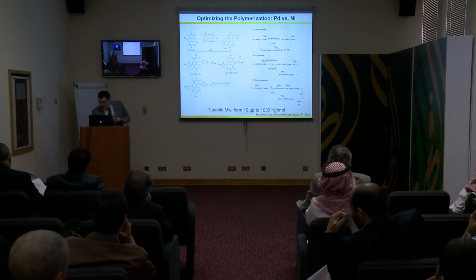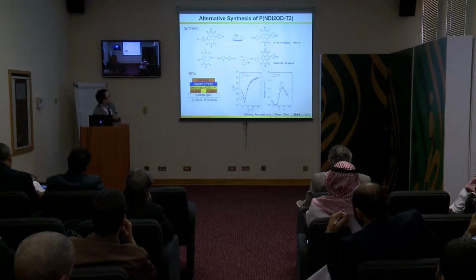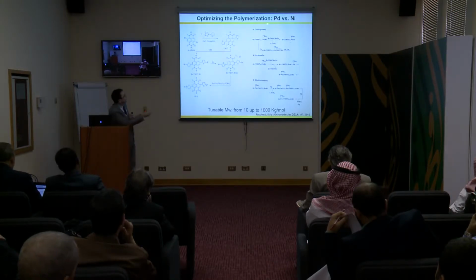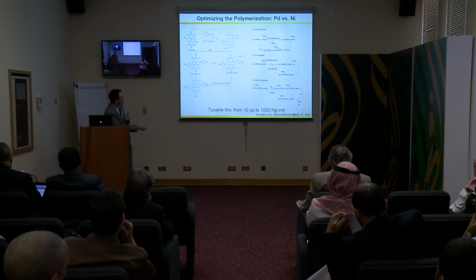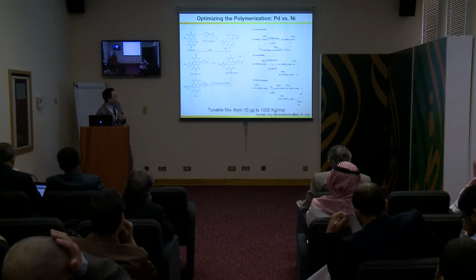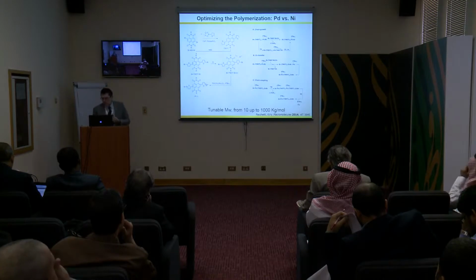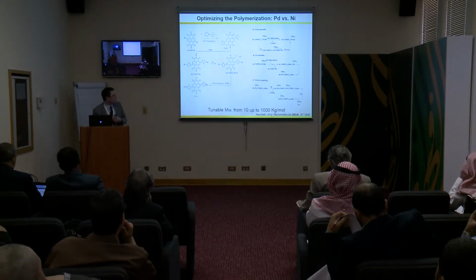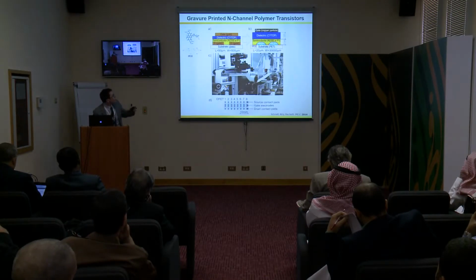In this type of approach, we use nickel as a catalyst. Nickel is not as active as palladium, and when we use palladium, we can tune the molecular weight in a very large range to make it much larger molecular weight if we want. So by tuning this, we can